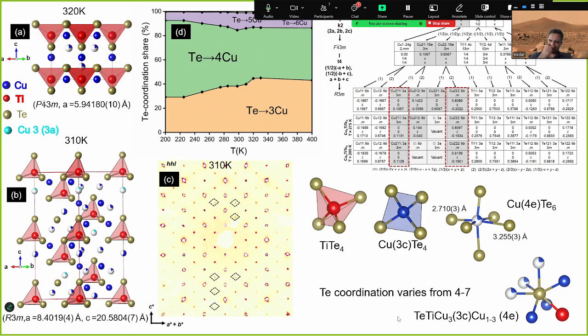The tellurium coordination varies from 4 to 7, because tellurium has 1 bond with titanium and 3 with the ordered copper. According to the availability of disordered copper, it varies from 4 to 6. There is another 3 actually. I think this can help explain the local coordination, as well as the thermal conductivity trend, because if the telluride coordinates with more copper, there is less availability of the lone pair of telluride, so the local distortion might be less.